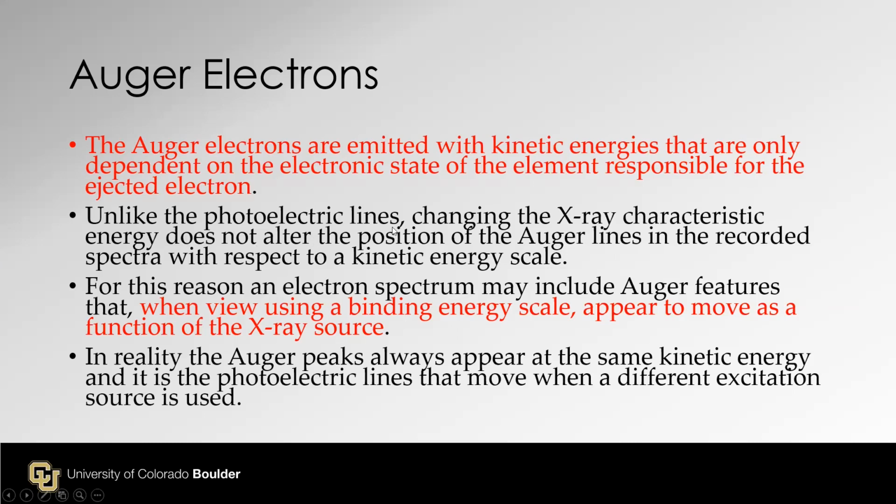Unlike the photoelectron lines, changing the X-ray characteristic energy does not alter the position of the Auger lines if we see it on a kinetic energy scale.